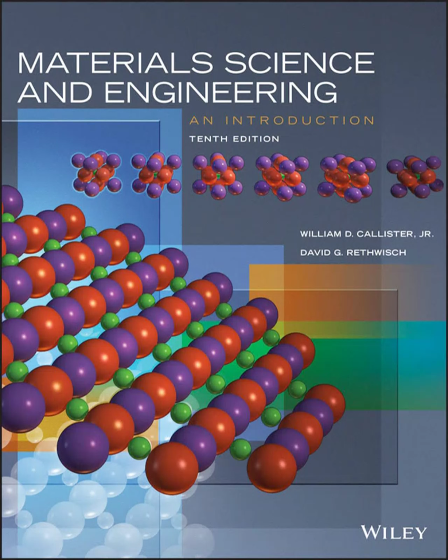Imagine a semi-infinite solid, basically. The material is thick enough that the diffusing atoms don't reach the other side during the process. And you hold the concentration right at the surface constant. This happens all the time in treatments like carburizing. Ah, like hardening the surface of that steel gear we started with. Precisely. You're diffusing carbon into the steel from a gas, keeping the surface carbon level constant. The solution for this involves a mathematical function called the Gaussian error function, often abbreviated ERF. The equation looks like (Cx - C0)/(Cs - C0) = 1 - erf(x/2√(Dt)).